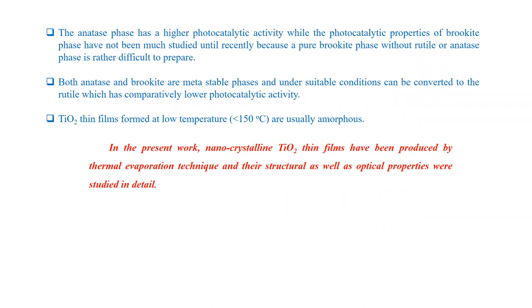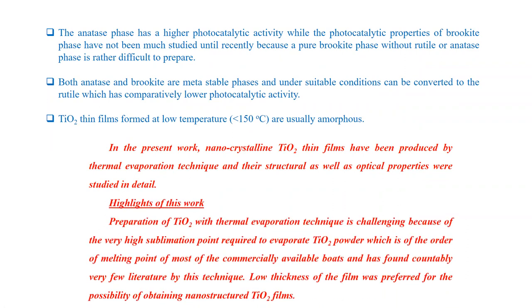TiO2 thin films formed at low temperatures are usually amorphous. In the present work, nanocrystalline TiO2 thin films have been produced by thermal evaporation technique and their structural as well as optical properties were studied. The main highlight of this work is the preparation of TiO2 by thermal evaporation, which is challenging because of the very high sublimation point required to evaporate TiO2 powder. Low film thickness was preferred to obtain nanostructured TiO2 films.